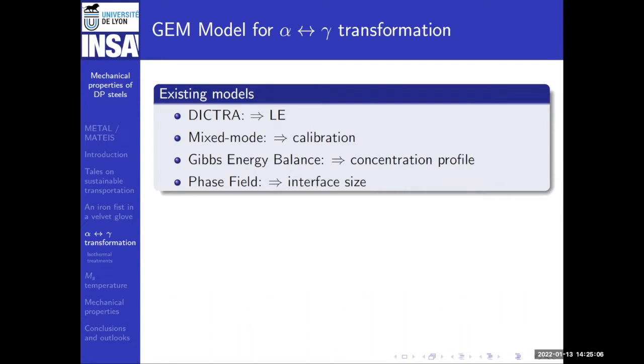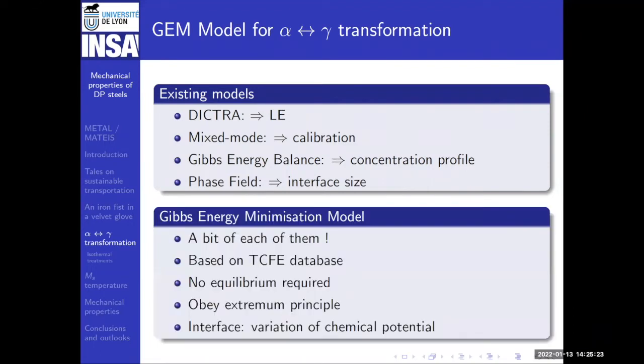But Dictra is based on local equilibrium, meaning equilibrium at the interface, which is not always the case. There are some other more elaborate models. Maybe the most elaborate one is phase field, that some of you may know. So what we did was we designed a new model which would take a bit of each of them, taking only the advantages. The idea is to have a thermodynamic database based on Thermo-Calc, without requiring any special equilibrium condition at the ferrite-austenite interface, and a model that obeys a simple principle: the direction that it will take is the one that minimizes the Gibbs energy function. That's why it's called the Gibbs energy minimum model. So it will choose the direction that minimizes the Gibbs energy.